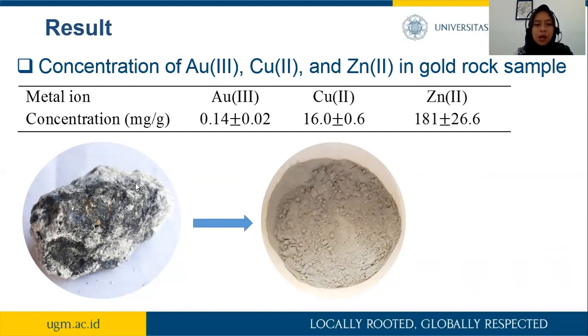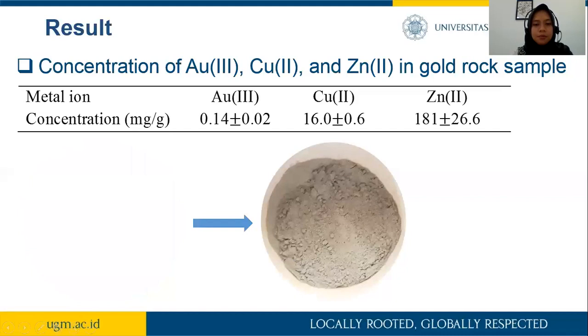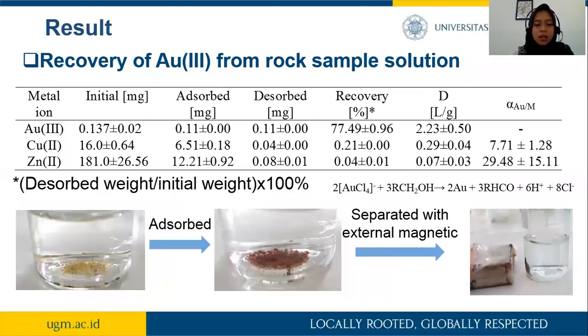This picture is our sample in rock form, and after that we crush or grind it and sieve it to 200 mesh. And next, the recovery of gold from the rock sample solution. The most abundant species is Au3+, which can be adsorbed by the adsorbent because the adsorbent has positive charge, under the condition below the zero-charge point of chitosan.